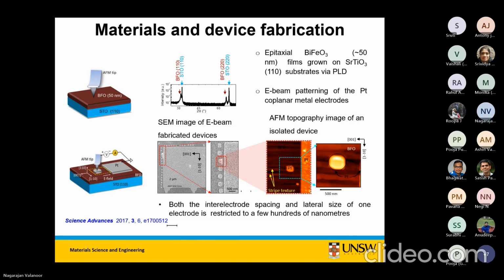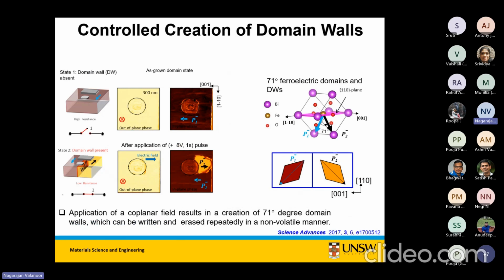And what we do is we make use of the fact that there is a very strict orientation relationship between the polarization, the crystallography, and the electric field to have a controlled creation of 71 and 109 degree. We actually did both. And it's shown up here that in the as grown state, this is a PFM image. The out of plane image shows that when I grow it, all the out of plane orientation is in one state, and all of the in plane orientation on the right side, that's in one state.